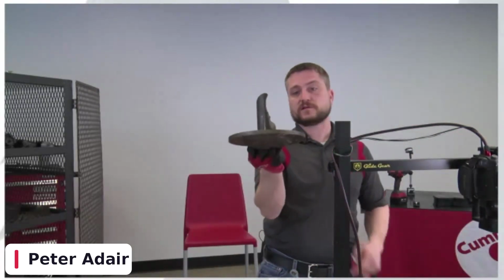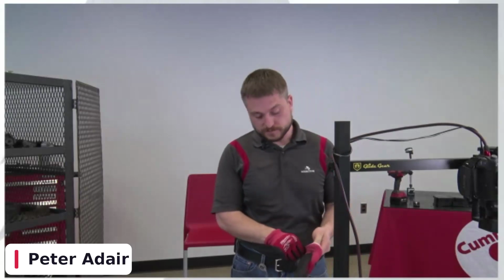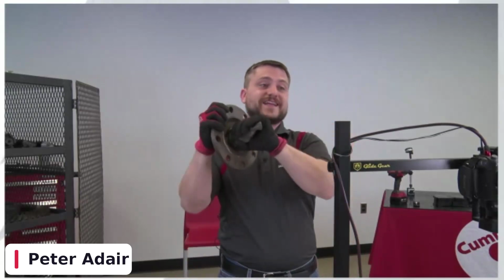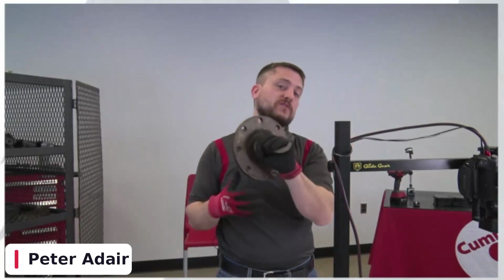Thank you. All right, so when we're looking at axle shafts, it's going to depend on the series because each series has a different diameter shaft. We can go anywhere from 280 degrees all the way up to like 420 degrees. Most of them will do 360 degrees, which is crazy when you think about a 1.5 inch, 2-inch diameter shaft twisting all the way around before it finally snapped off.